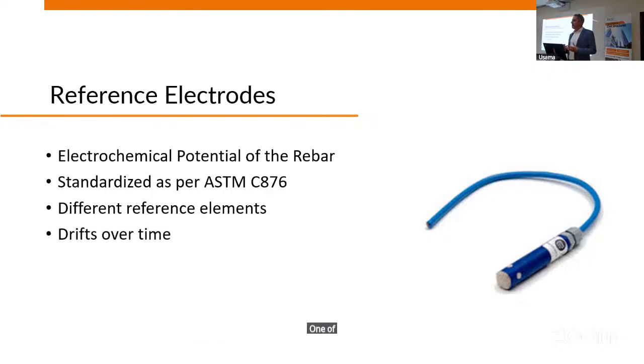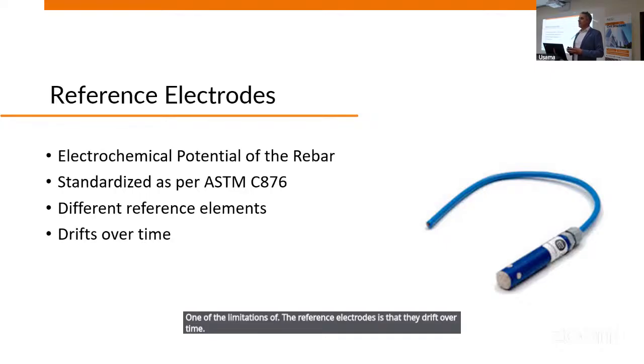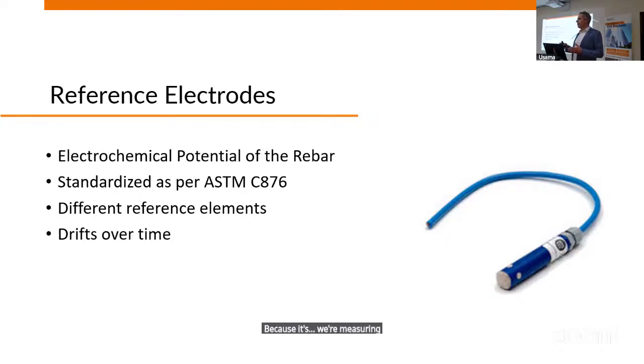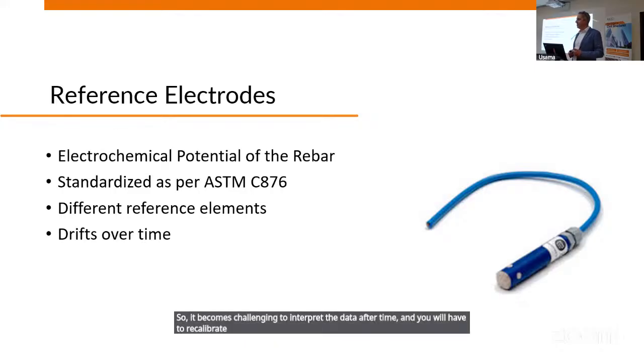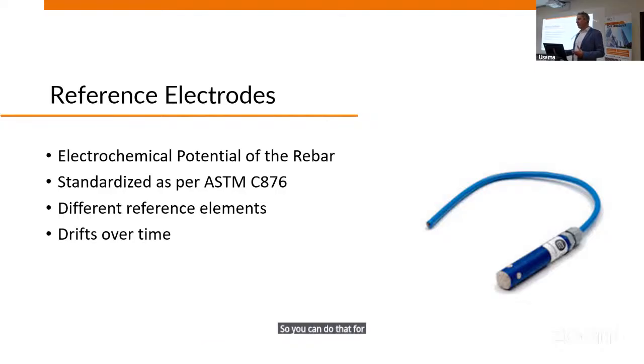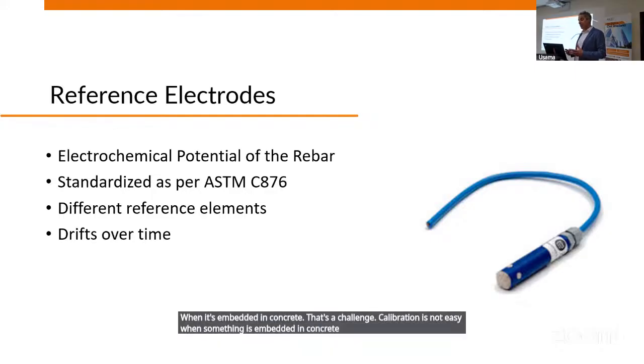One of the limitations of reference electrodes is that they drift over time. Because we're measuring potential of rebar, of steel in concrete, versus a totally different material. Over time, they drift separately. So it becomes challenging to interpret the data after time, and you will have to recalibrate continuously. So you can do that for portable reference electrodes. It's quite easy. So as an inspection tool, it's quite effective. But when it's embedded in concrete, that's a challenge. Calibration is not easy when something is embedded in concrete. It's doable, but it's not simple.